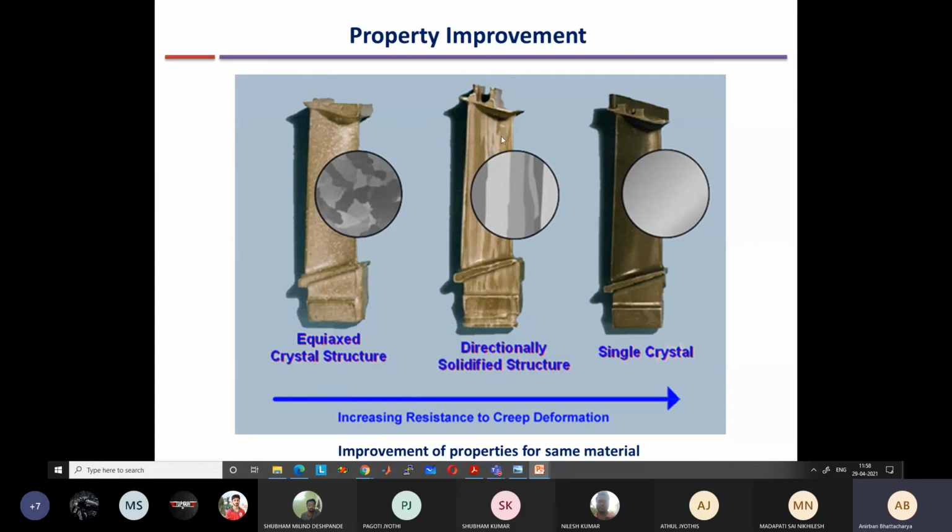This is known as creep, and because of this elongation, the blade may strike the casing, and it may lead to catastrophic failure. So creep is a big problem in turbine blades. When I was saying in the previous classes, in power plant engineering or gas turbines, that temperature is limited by the temperature of the turbine blade, whatever turbine blades can sustain, it is the temperature at which creep is very low.